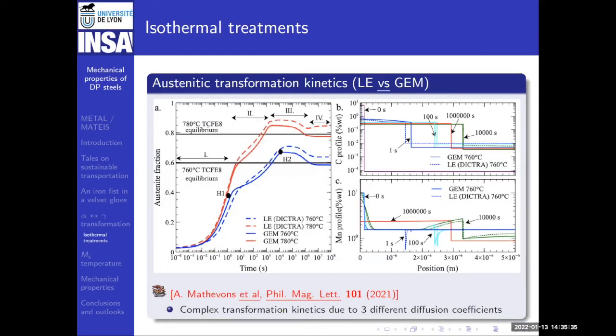So here we compare the model that we just discussed with a classical formalism, and we compare the profile. We see that they are almost the same. That's the thing to remember here. Or just, if I want to be mean, I can underline that DICTRA does not respect the mass balance. So DICTRA is not in agreement with Thermocalc, which is strange because the same company is selling the two modeling tools. That was something that was funny because the Thermocalc model is here and DICTRA ends up with a different value at the end, which is not the case for the fixed energy minimization model.